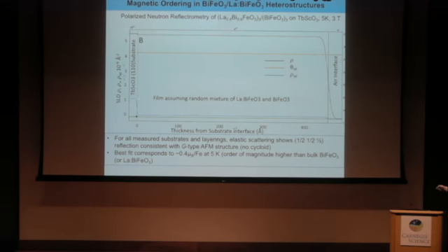So then I have my magnetic profile, and I see a really high magnetization in my substrate. But my fits always converge to something that looks like a uniform magnetization. In this case, I'm not allowing the magnetization to oscillate with the periodicity of the superlattice, just out of interest of getting a nicely fitting model.